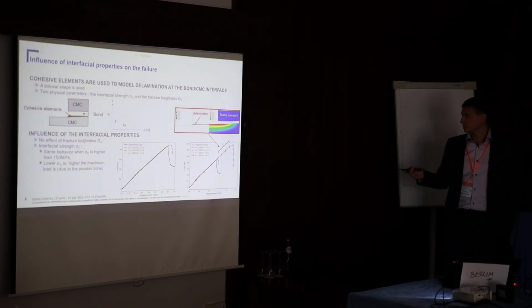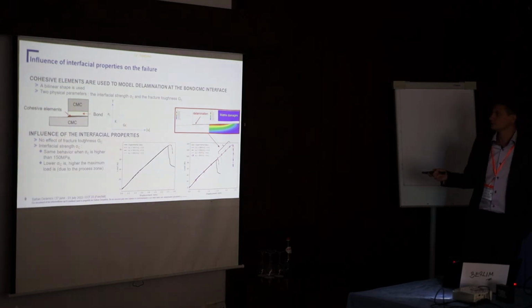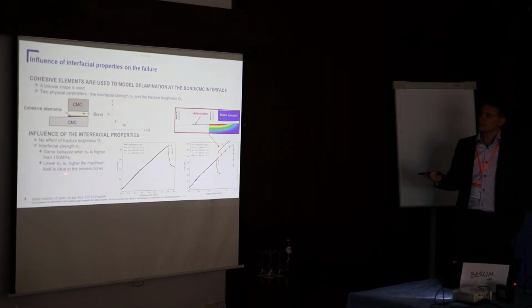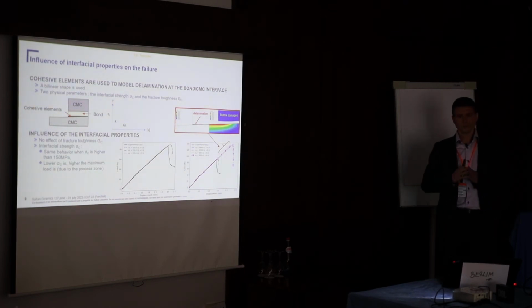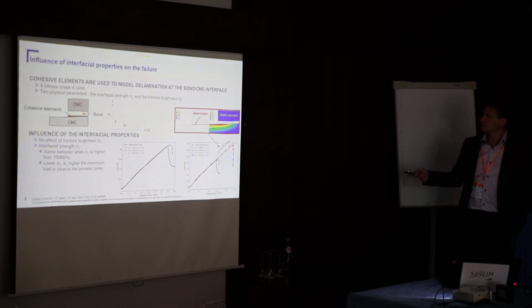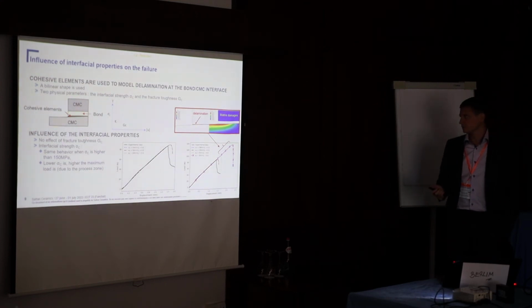The explanation of this kind of mechanism is due to the fact that when we use a low interfacial strength value in the cohesive zone model, we have a larger process zone. The process zone is the length where the cohesive zone model is damaged but not yet broken. Okay, so when this process zone is larger, we add softening behavior to the structure, and due to the softening, the stress in the CMC substrate is lower. So we have not attained the threshold that we need to have yarn failure. So this is why we have delamination for this value, and then the yarn failure of the CMC substrate.